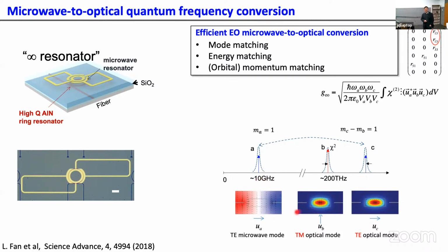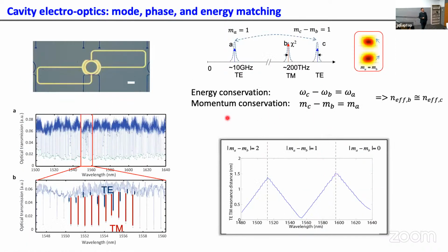So the way we do that is to create an angular momentum in the microwave mode by building this ring resonator to have an angular momentum equal to 1. Then we engineer the TE mode and TM optical mode to have azimuthal numbers that differ by 1. In this way, you can get the phase matching. So you do spectroscopy with the optical mode here. The azimuthal mode numbers are very big, around 1,000. When they couple, you can see the transmission and the mode splitting, and you can know that the TE and TM modes have the same azimuthal number.